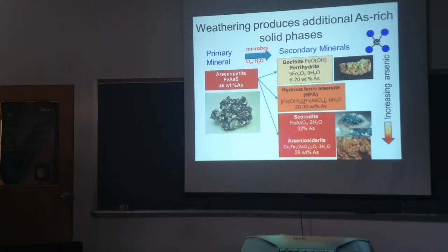And then finally, there's some arsenate minerals, scorodite and arseniosiderite, which have AsO4, the most oxidized form of arsenic. That's arsenic 5+ combined with oxygen to make AsO4, which has a net charge of -3. So ferric iron +3, arsenate -3, and water of hydration. That mineral has 32% arsenic, and it turns out to be not that bioavailable, but arseniosiderite, which has calcium in it, turns out to be one of the most bioavailable phases. So just because it's in the arsenate form doesn't necessarily make it super bioavailable, but it turns out the most bioavailable phases are calcium-bearing iron arsenates.